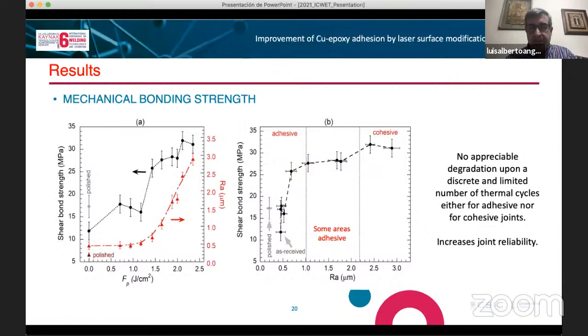If we plot the shear bond strength as a function of the roughness, we see that at the beginning, when we apply a low fluence value, the roughness increases very little, and all the behavior is adhesive.